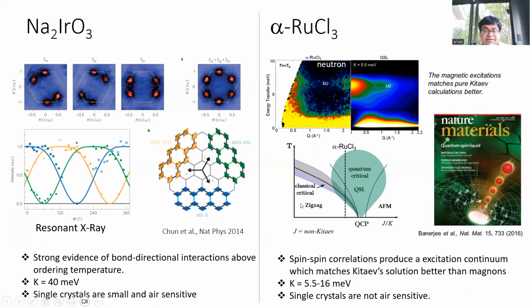What we showed is that this material is not quite at the quantum critical point, not quite in a quantum spin liquid state, but it was pretty close, where at low temperature, you do see some zigzag type antiferromagnetic ordering, but when you go to slightly higher temperature and you kill that zigzag ordering state, you get some of the quantum critical behavior coming in from the quantum spin liquid,